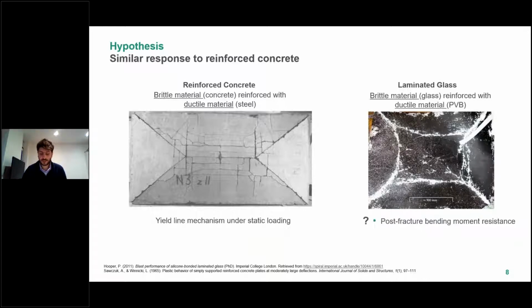To achieve this, I first examined if there is any residual post-fracture bending moment capacity in laminated glass following the fracturing of the glass layers. My second objective was to assess if the effects of inertia experienced by laminated glass panels during a blast event are responsible for the different pattern observed, compared to the well-known yield line pattern forming under static loading in reinforced concrete and other ductile materials.